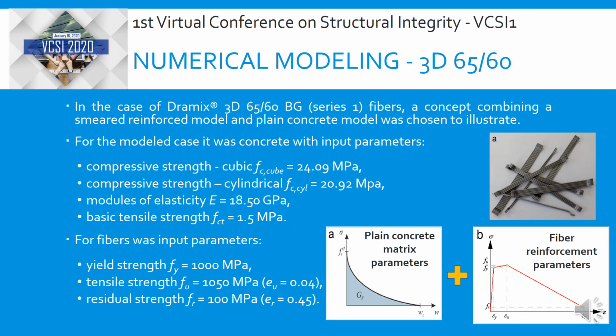In the case of Dramix with hooked ends fibers, series 1, a concept combining a smeared reinforcement model and a plain concrete model was chosen. For the modeled case, it was concrete with input parameters: compressive strength for cube 24, compressive strength for cylinder 20, modulus of elasticity 18.5, basic tensile strength 1.5. For fibers the input parameters were yield strength 1000, tensile strength 1050 and residual strength 100.